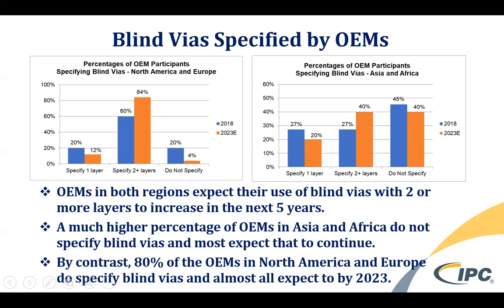So you do see, and again, while much of the industry is one layer down, basically surface to the next layer, we also see a significant growth in going down to 2+ layers. So going from layer 1 to layer 3 or layer 1 to layer 4. So it's a very good possibility that you'll be seeing more designs as a fabricator to develop and process circuit boards with these higher aspect ratio boards, and therefore these vias going down to multiple layers.